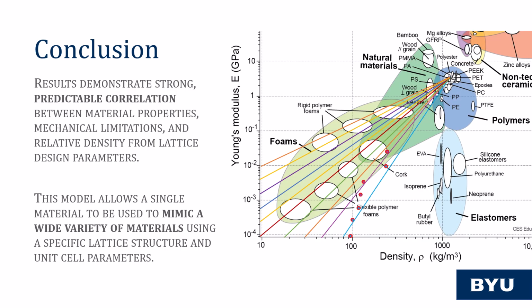In conclusion, a model was created that accurately predicted the behavior of lattice designs. The model proved a strong correlation between cell pattern, strut thickness, and cell size to the stiffness, strength, and relative density of the part. Expanding this model could map linear relations between the bulk materials and softer, compliant counterparts. Having the relations sufficiently modeled would then allow one to mimic compliant or lightweight materials using only the geometry of the part.